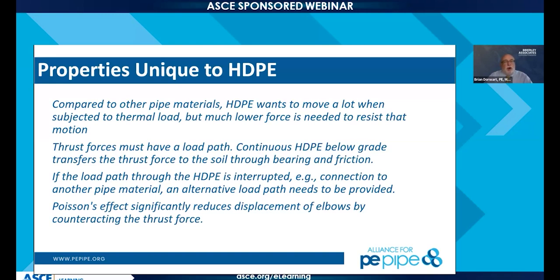Other things, if you have a non-pressure pipe as a gravity pipe and it's in the ground below the recommended depths for no concern, you start getting into an area where, with deeper and deeper installations, you need to consider your soil loads on your pipe for long-term loads. Because as that pipe creeps, if your soil is really soft, like just silts in a river, the pipe can start deforming over time. So you want to look at your modulus, which includes a creep factor. It's not really a true modulus, as far as design's concerned.